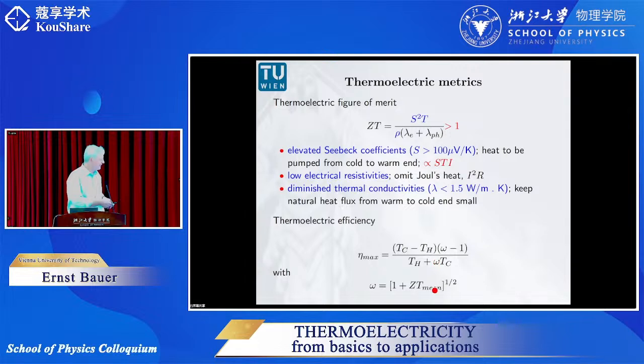Third, as you can see here from this formula, the figure of merit, that means the material quality, just enters as the square root of ZT. That means if we are working hard for 10 years and improve a certain material's figure of merit from 1 to 2, finally we improve the thermoelectric performance just by a factor of 1.4.